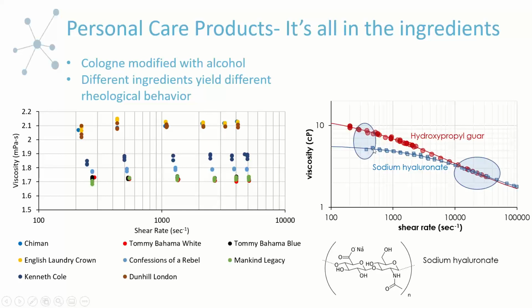So low shear is what it behaves like under storage conditions, or when you're first acquiring the sample from whatever container you have it in. And then the high shear environment is likely what it experiences under use. So as we can see here, sodium hyaluronate has a lower viscosity than hydroxypropyl guar at this low shear rate range, but at the high shear rate under application environment, they begin to behave similarly. So the customer will not really be able to tell a difference. So this can help guide, say, your quality control, for instance.